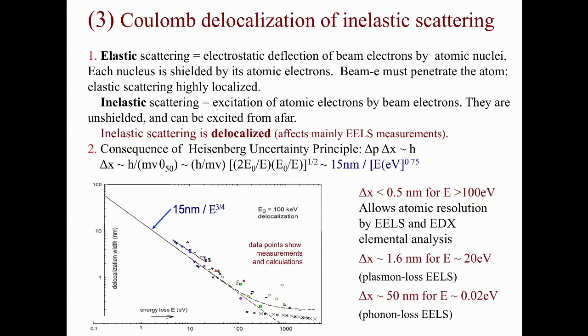A third factor affecting spatial resolution, particularly in EELS, is Coulomb delocalization. Our analytical signal is a result of the excitation of atomic electrons. They lie outside the nuclei of each atom and can be excited from some distance away by the Coulomb field of a beam electron. Another way of viewing this effect is as a consequence of the Heisenberg uncertainty principle. The small inelastic scattering angles now appear as a disadvantage because after scattering, the transverse momentum, delta P, is small, and the uncertainty in lateral position of the scattering event is therefore large.